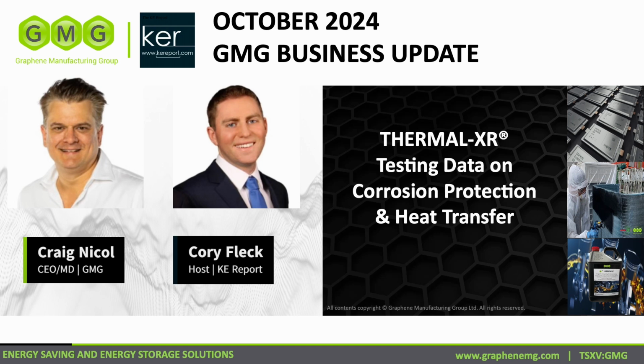But the other point, which is probably more significant, which to our knowledge is the only company or product out there like this, which clearly outlines that our coating can increase the thermal radiation of aluminium by around 8 times. And then if you account for the natural air cooling, then we're actually about 2.2 times more heat transfer when you have our coating as against just having bare aluminium. And that is an astounding number. Now this is at 100 degrees Celsius. It's a bit less, obviously, the lower the temperature, but it is an astounding number, and it shows that we can now understand what this coating can offer.